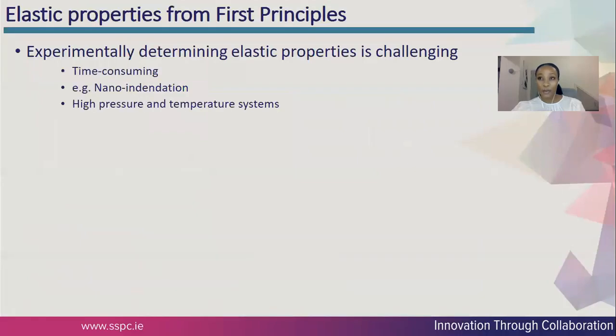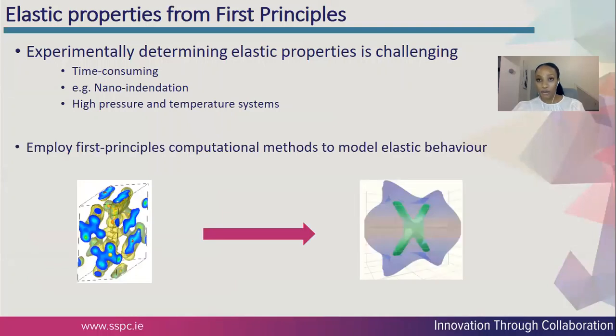Even more so because experimentally determining elastic properties can be difficult at times. For example, the requirement of specially grown crystals and long preparation times poses a limitation. And in certain instances, experiments can even offer limited information, like with nanoindentation, where information can only be obtained on certain crystal faces. In certain cases, it is even impossible to obtain elastic properties, such as in high pressure and high temperature systems, and also metastable systems. So employing computational methods can allow us to model and extensively characterize mechanical behavior.